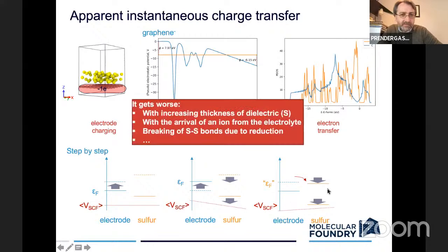Okay, so it gets worse. Obviously, this potential and its slope, it continues on forever, right? And so if you have an increasing thickness of dielectric, then even if the immediate molecules next to the electrode are not getting reduced, there will be another one at a lower potential, and then another at even lower potential. Eventually, you'll find one, as you get thick enough, that will accept this electron. And it gets worse again if an ion arrives from the electrolyte, because now that ion is amplifying the electric field. It creates a capacitance. And then once these electrons arrive on the molecules of sulfur, what we've said is already that you'll start to break bonds. And so some chemistry will start to happen. And now you're going down this kind of irreversible path that you can't come back from.